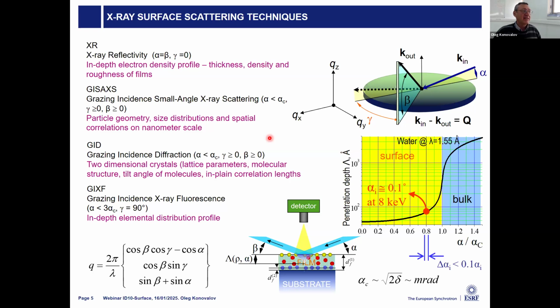Nowadays, when people more and more work with nanoparticles, these two regimes can merge together, because we work in a small angle regime, but we measure diffraction because we see how some units are ordered in space systematically. So we may measure Bragg diffraction at a very small angle, like in the SAXS regime. But historically, if we measure at a small angle, this is GISAXS, and then we can get information about particle geometry, size distribution, and particle correlations on the nanometric scale.